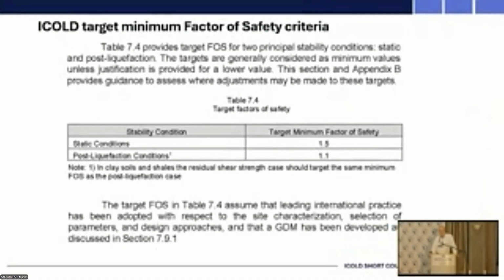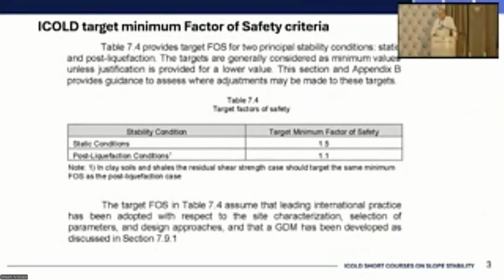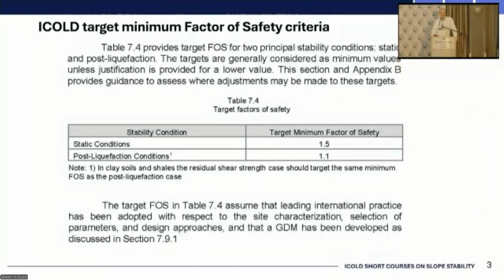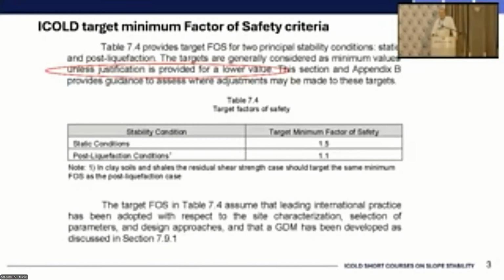In the main bulletin segment, you'll find this table 7.4, and it provides the recommended factors, minimum target factors of safety for 2 stability conditions. The static condition, which applies to both drained and undrained shear strengths, and then what we called in the bulletin the post-liquefaction condition. And I will say that, well, let me just say that to start with, these are minimum target values, and they're to be used unless justification can be provided for a lower value. And that's where Appendix B comes in, is providing a logical basis to deviate from these target minimums. And so what I said on the post-liquefaction, it's not my favorite term either. Andy has talked about he doesn't like residual strength. He's not alone in that.